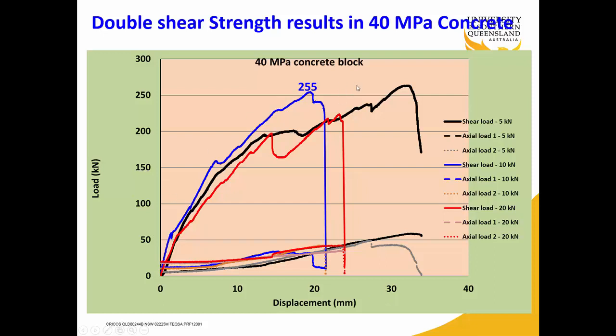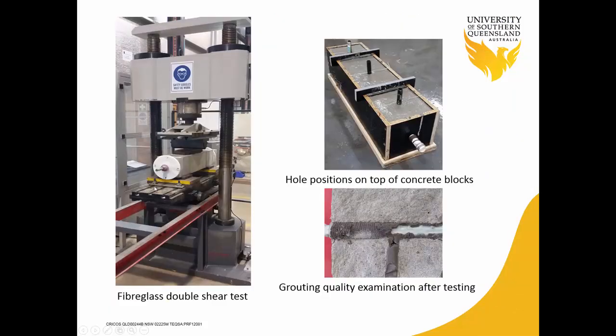Bearing in mind that because we are doing double shearing, the value that we achieve should be divided by two in order to come up with the shear strength of the whole system, rather than the sample. The top data here shows shear, and below it shows the axial load. If I go back to this slide, a load cell was positioned behind this barrel and wedge to measure the variation of axial load